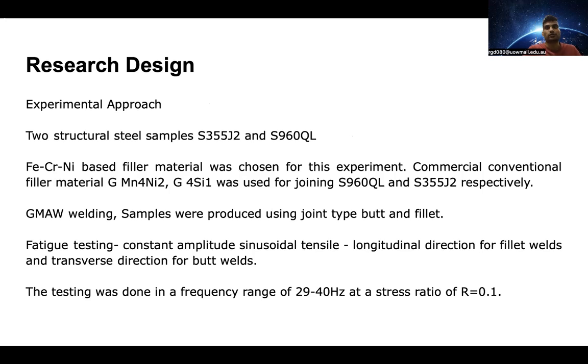For the research design, we took an experimental approach. We used two structural steel samples, S355J2 and S960QL. An iron, chromium, nickel-based filler material was chosen for this experiment in conjunction with commercial filler materials of G Mn4Ni2 and G4Si1 for joining. The welding process used for the experiment was gas metal arc welding, and samples were produced in both butt weld and fillet weld configurations.